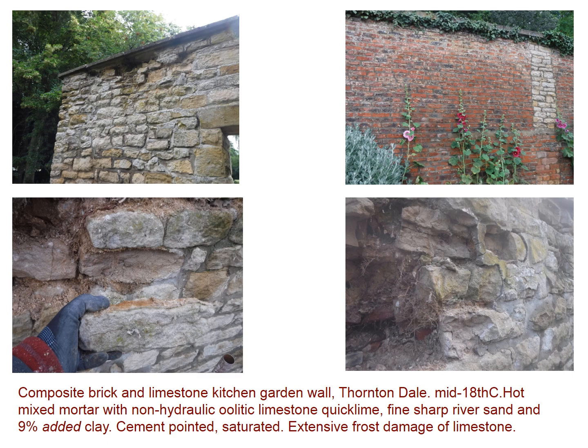led to extensive frost damage of the oolitic limestone, which of course has a perfectly optimal pore size distribution as well, being calcium carbonate. The frost damage to this stonework is far more extensive than is apparent in these photographs, as I discovered when I had to repair it. Interestingly, of course, the original mortars were earth lime, one would say, looking at them, but on analysis were made with the very finest sharp river sand, with 9% clay actually added by the masons deliberately.